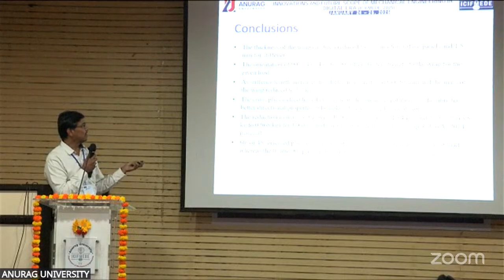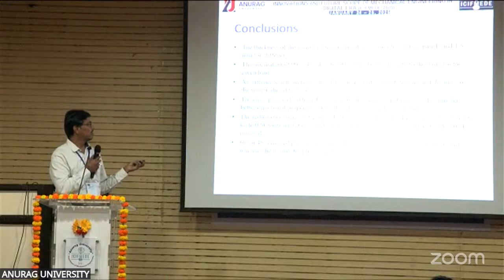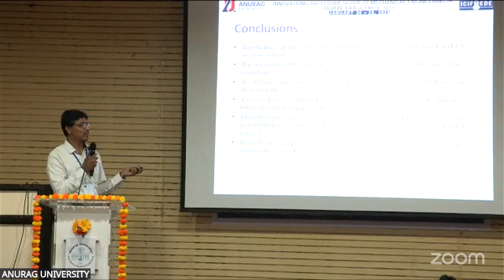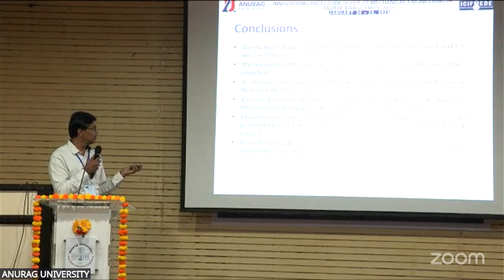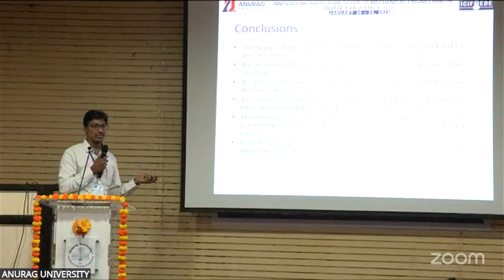The cross ply indeed had better load withstanding capabilities as the fiber has better directional properties. And as we have seen, the reduction in mass was there for e-glass. It was 61.7%. So the initial aluminum one was 3.5 kg and it reduced to 1.34 kg. And when we use carbon epoxy, it reduced, sorry, from 3.5 to 0.968 kg. And 60 to 45 degree orientation plies were responsible for bearing the maximum amount of load, whereas 0 and 90 degree plies help in maintaining the structural integrity.